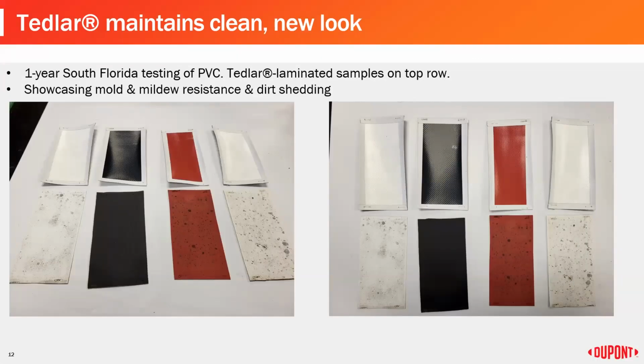So this is actually not on metal, but this is just a test we did, a very extreme example, on PVC. So this is what people would use for an awning or some sort of fabric structure. We tested clear Tedlar and then no Tedlar. So you see within 1 year of South Florida testing, the other side, the non-Tedlar protected, has absolutely molded, mildewed, filthy. Metal's not going to do it quite as badly as this. This is an extreme example, but you see how well it protects even this, kind of cheap material that has a tendency to get gross. Tedlar is going to protect that. And we'll keep this test running for 10 plus years, and I'm sure it's going to look just as good.